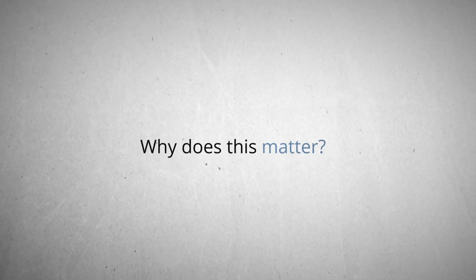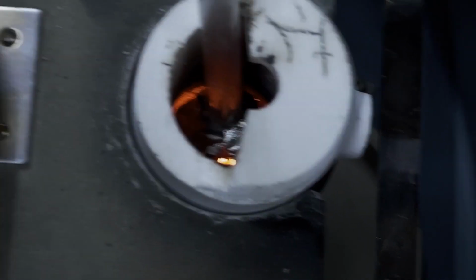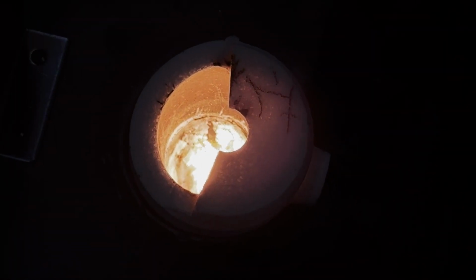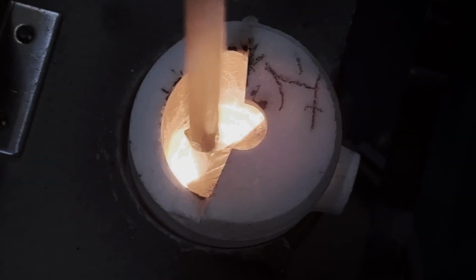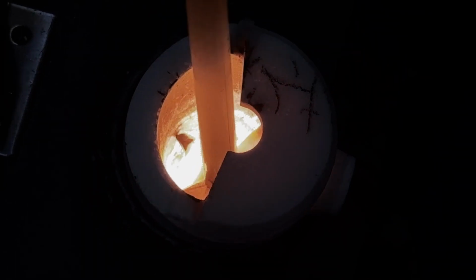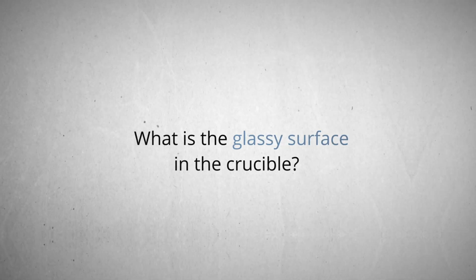Why does this matter? Because that glassy surface can cause brittleness to our platinum metal, and it is a source of contamination. And this effect will stack every time we reuse metal, like the buttons and the scraps, especially if we're not adding new metal into the mix in every subsequent cast. And this problem of brittleness will become increasingly obvious. How brittle, you might ask? I've seen spruce snap off a tree with my bare hands kind of brittle, and we don't want that for our jewelry. So what is this layer of glassy surface in our crucible anyway?